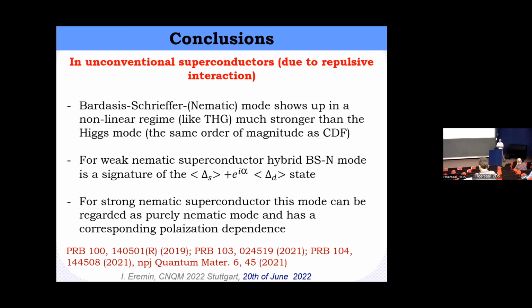But if you are lucky, the second mode, which appears at energies lower than the 2 delta, is very likely a mode coming from the subdominant superconducting channel. And in the case where there is an additional particle-hole instability, and I believe the same can be said if you have coexistence with a spin density wave state as well, the properties of this mode will be dominated by the particle-hole instability, like the nematic instability I was discussing.